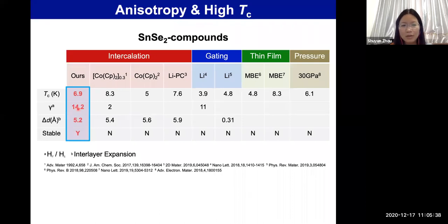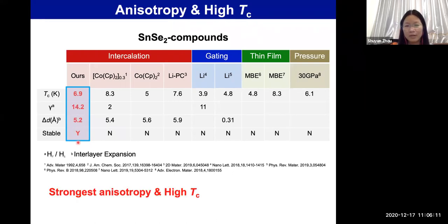anisotropy. Here, this is the in-plane upper critical magnetic field over the out-of-plane magnetic field, to indicate how anisotropic it is. And here we see that this intercalated sample is quite anisotropic compared to intercalation using other ions before. And moreover, the sample is again very stable in the air. So by using this intercalation method, we can obtain high TC and strong anisotropy at the same time.